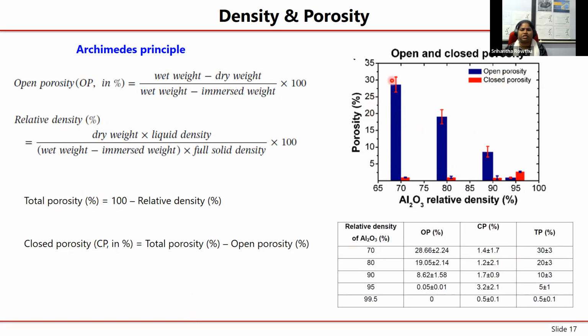Essentially, what is happening is that in the 70, 80 and 90, definitely when the total porosity is decreasing, your open porosity will also decrease, which is okay. What you have to remember here is, if you look at the closed porosity values, it is not changing much. So it means that until 90% density or so, most of the porosity is actually open. However, for the 95%, you see that closed porosity is much more compared to the open porosity in that material. And definitely for the 99.5, then you don't have any porosity, or let's say not a very significant amount of porosity is present. So that's the porosity information.